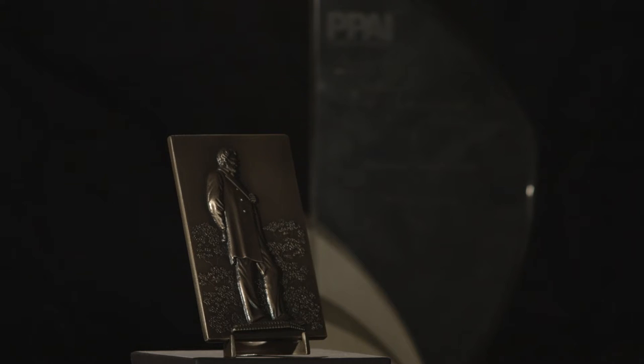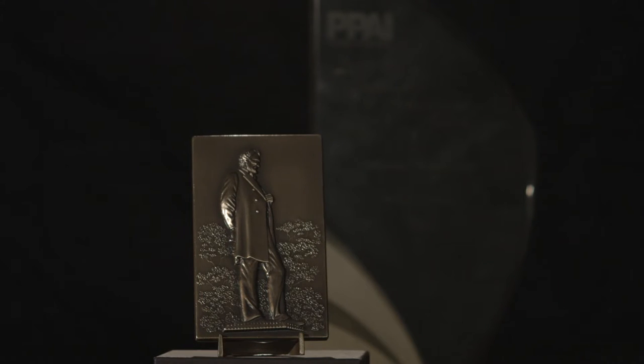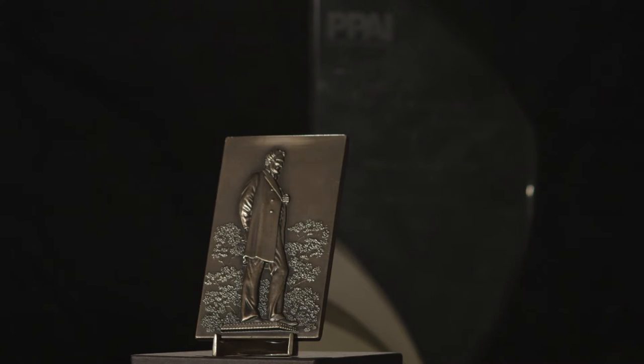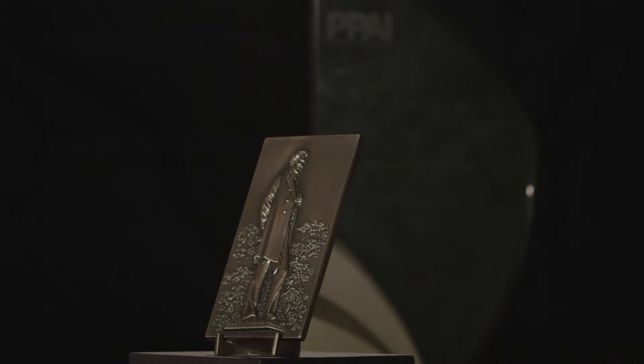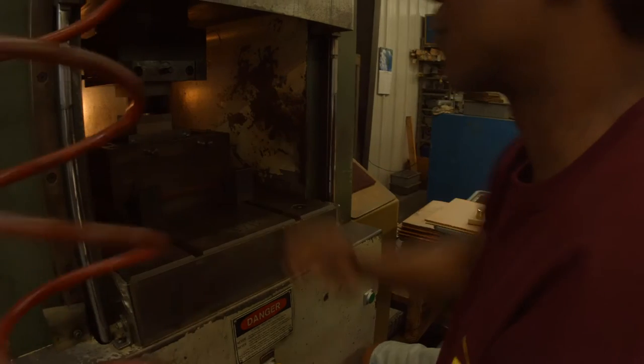First up is the Chicago Coin Club Abraham Lincoln Medallion that we won for metal striking. It is a high-relief, die-struck brass medallion, multiple-struck with annealing between strikes, and then finished in our museum bronze finish. This is our die-striking process.